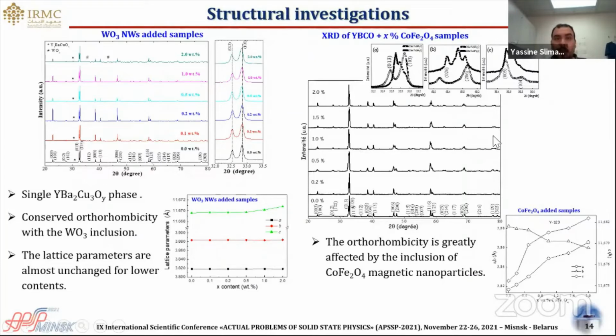Opposite to this example, it is clear here that the inclusion of magnetic nanoparticles greatly affected the different lattice parameters and the orthorhombicity, which reduces gradually with increasing content of additive. So depending on the objective, we can select the appropriate nanomaterials for doping.